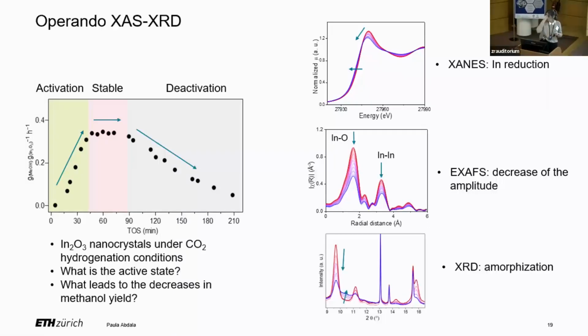And when we look at the powder diffraction data collected in a quasi-simultaneous fashion, what we see is that the initially well-crystalline indium oxide nanoparticles, or nanocrystals, amorphize as the time on stream passes.